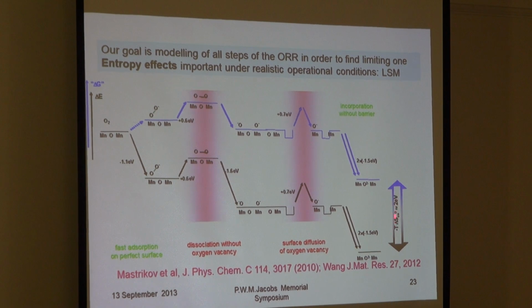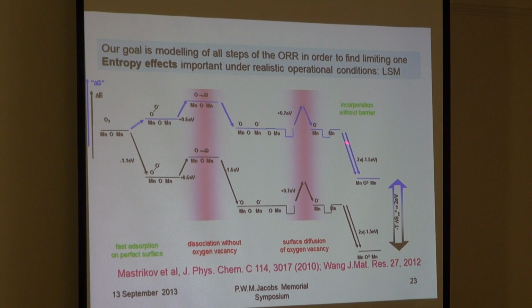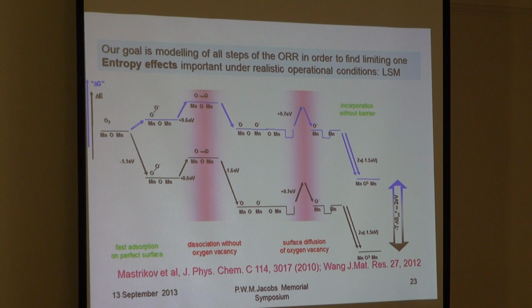So essentially this entropy contribution could be about 2 electron volts at an operation temperature of 1000 Kelvin. And it means that this diagram of 0 Kelvin should be modified, at least in zero approximation, by this one, which is blue now. And instead of energy gain due to oxygen molecular absorption, essentially you need some energy to absorb oxygen,